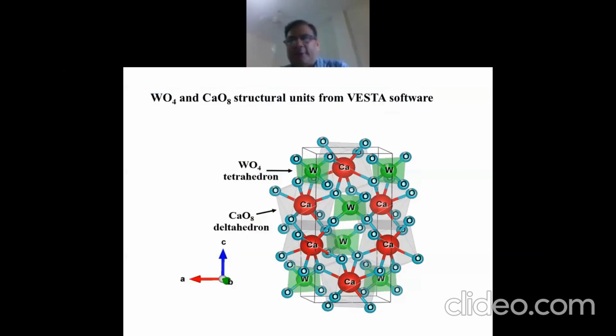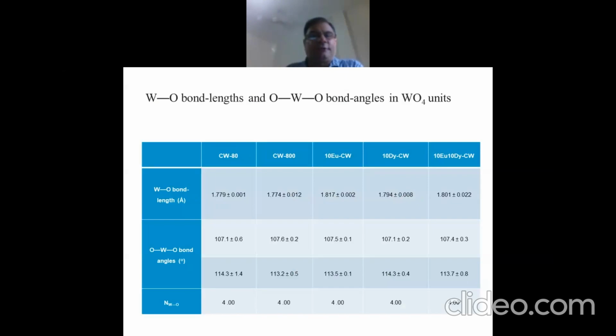Once you do the Rietveld fitting, you can determine the lattice parameters, the unit cell parameters a, b, c, alpha, beta, gamma, and also the coordinates of the atoms in the lattice, and you can determine the short range structure. So the W ions have tetrahedral coordination, whereas the calcium ions have a coordination number of 8.